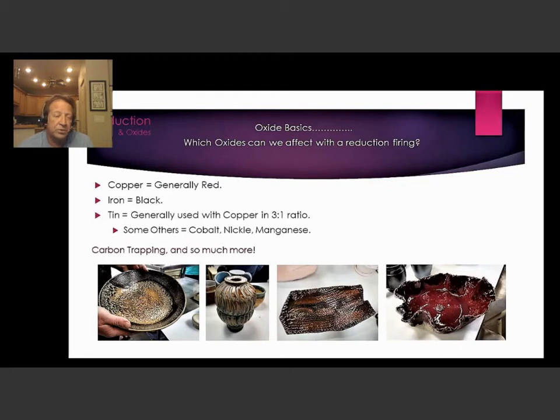Well, copper's at the top of the list. Goes from green to red. Iron goes to black, but you never see black because it reoxidizes and turns rusty. And tin, which is really used with copper mostly in a 3-to-1 ratio. There's others. Cobalt will be affected, nickel, manganese, and much more. But it's not only about colors or changing the colors of your oxides.